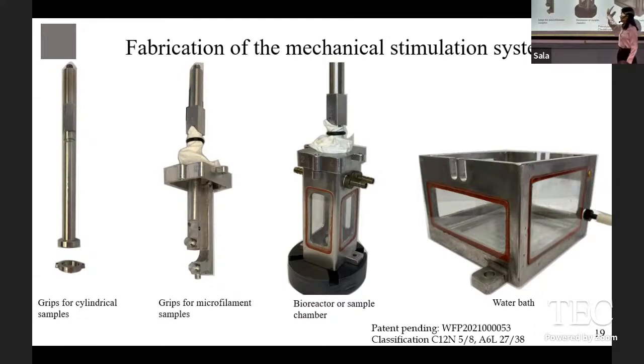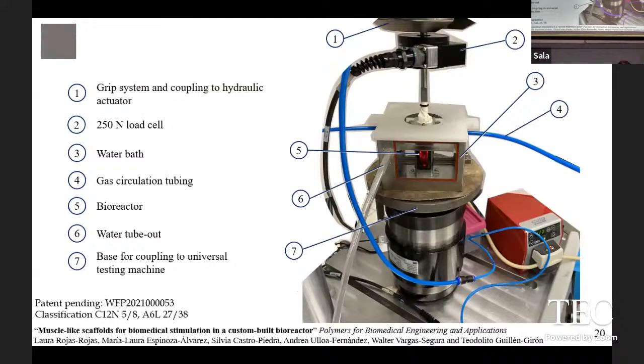Also, we fabricated a bioreactor or sample chamber that allowed us to do the growing of the scaffold inside. It also had some inlet and outlet ports on each side, and the top grip that is shown on the top can move freely to transmit mechanical loadings. To be able to control the temperature, we used a water bath that surrounds the bioreactor. So in this next slide, I can show you the assembled system in the universal testing machine.